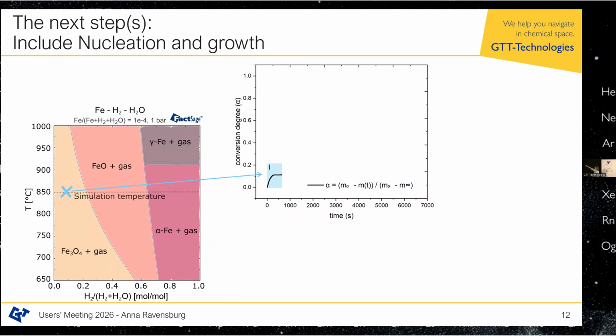It doesn't go up to 1. It goes up to approximately 1/9, because if you convert Fe2O3 to Fe3O4, approximately 1/9 of your oxygen atoms go away, and that's where it converts. You can also see that it approaches this, and then it stops there because it cannot go any further, because it's not thermodynamically stable to form, for example, wüstite. So we can look at this conversion, and then when we have fully converged to Fe3O4, we can do a next step.